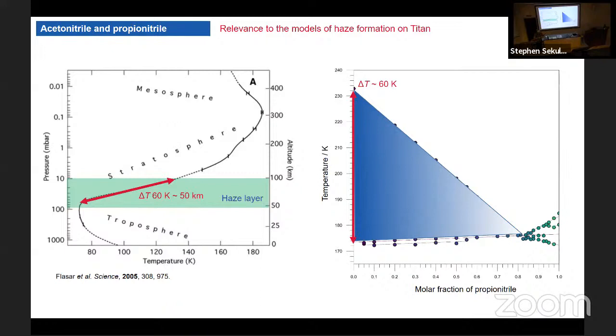altitude. This is important because, as I said, for example, propionitrile is not being identified in the haze. We may be looking at a different altitude. We might expect crystals of these nitriles at a certain altitude, but because they're mixed and not alone in pure phase, we may encounter them at a different altitude. And this is just a mixture of two, but as you can imagine, Titan is a mixture on a planetary scale. So we definitely need to work a little bit more in the direction of figuring out what is going on.